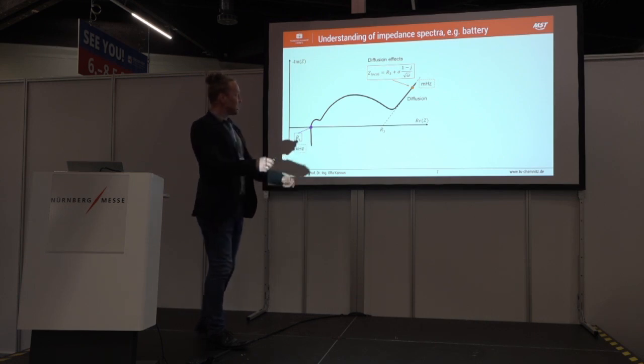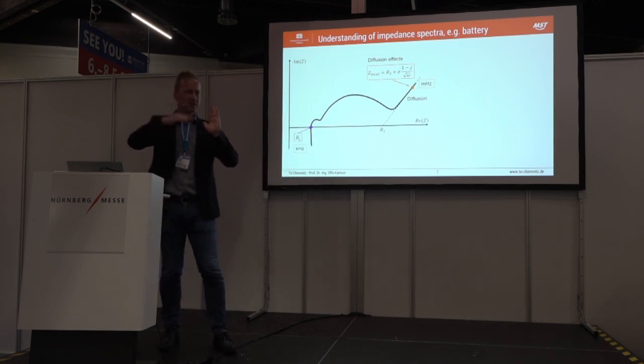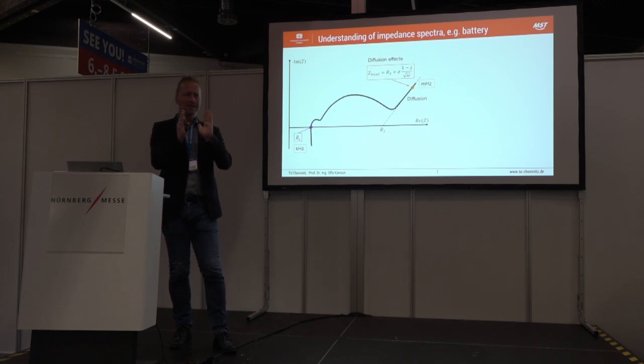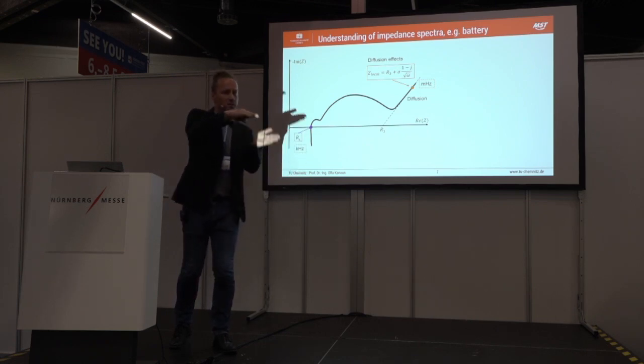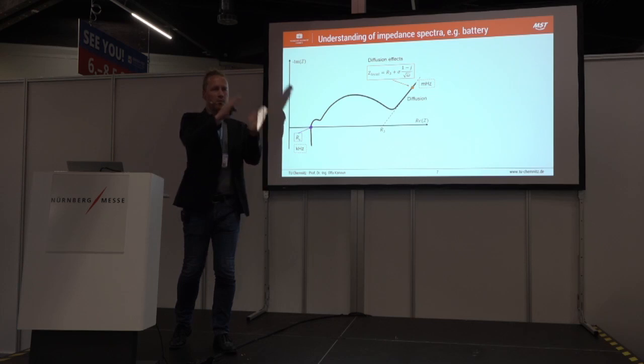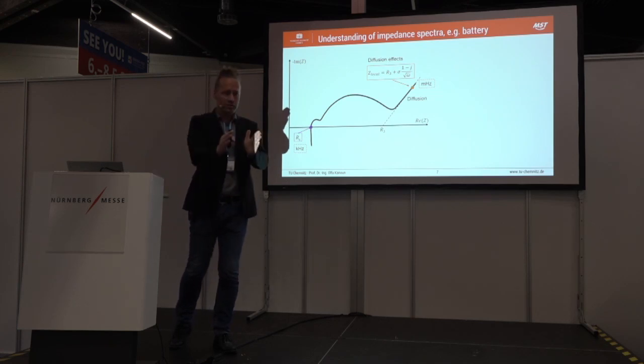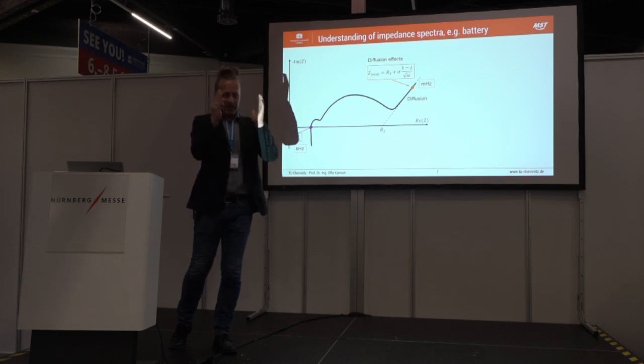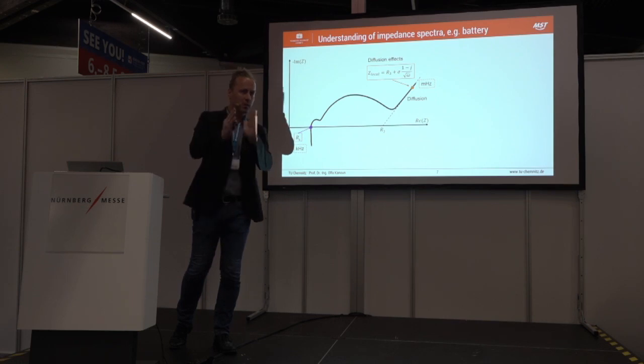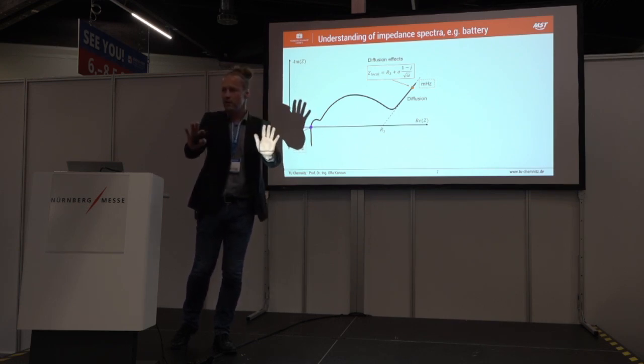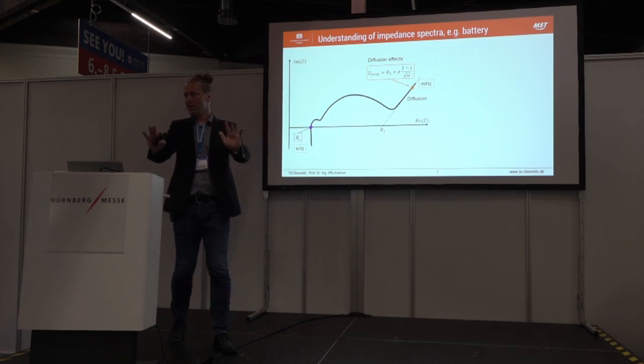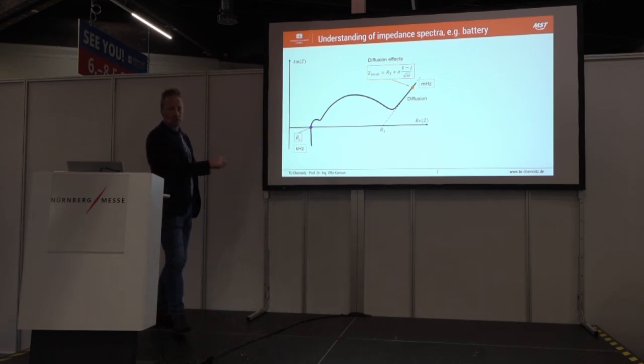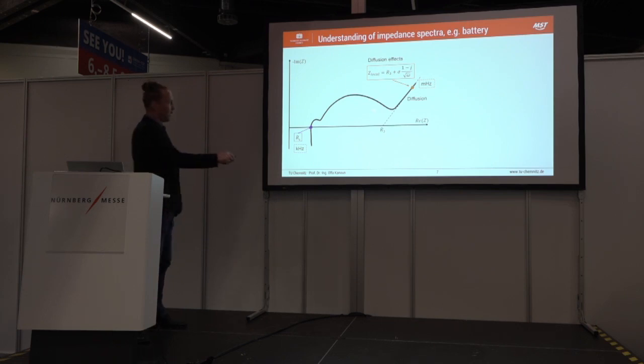So you need to understand, we have this excitation signal, a low frequency. At the end, it's a polarization of the molecules from the electrolyte. But the electrolyte molecules are very huge. And if you increase the frequency, the heavy weight of these molecules is too much, so they cannot follow the polarization, the excitation, anymore. That's why this phenomenon drops out of the contribution to the measured signal. And this is this point.